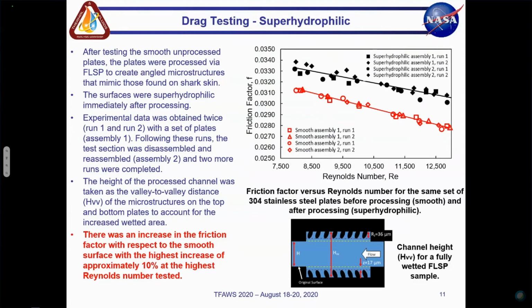So after testing the smooth unprocessed plates, we processed these via FLSP to get the angle microstructures. Originally, they are superhydrophilic after processing. So if you were to put a droplet, it wicks or expands over the surface, kind of like you would see with a porous material. So we put these plates into the channel. The experimental data was obtained twice, 2 runs each, and then we had 2 different assemblies to show repeatability.